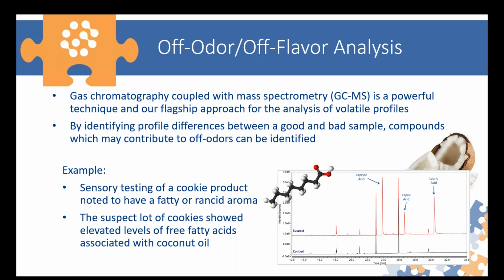And what we found is that the off flavor sample contained a number of compounds not present in the control. So on this chromatogram, on the bottom in black, we have the control sample, and on the top in red, we have the suspect sample. As you can see, there are three very distinct peaks there not present in the control. These were identified as caprylic, capric, and lauric acid, which are free fatty acids.